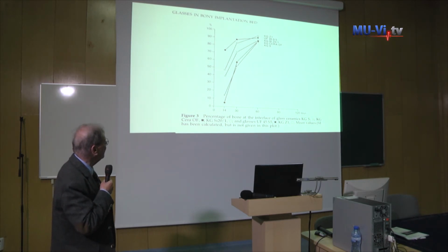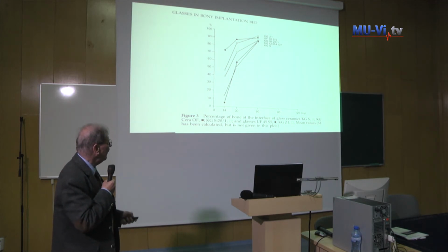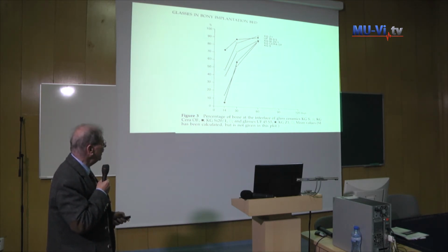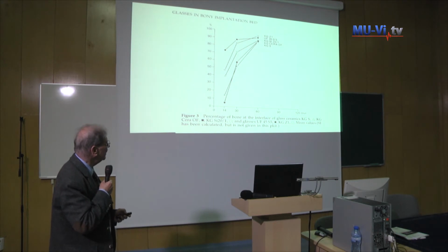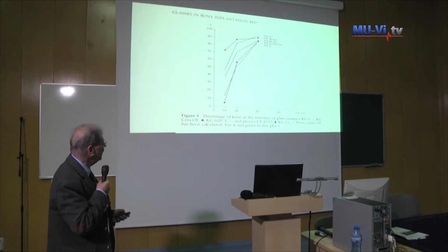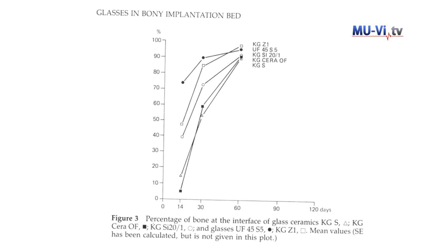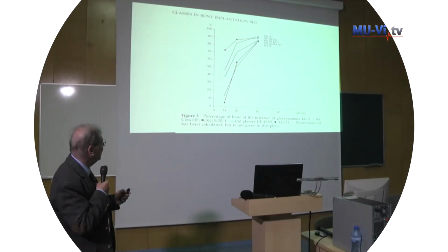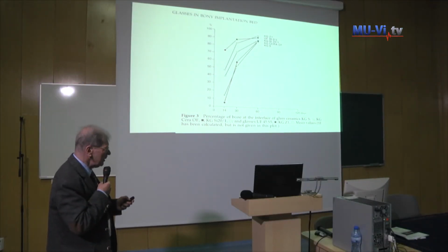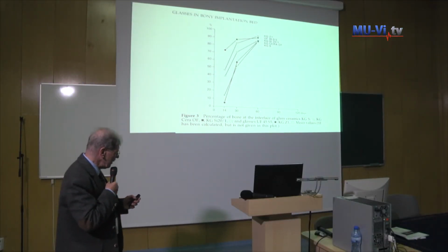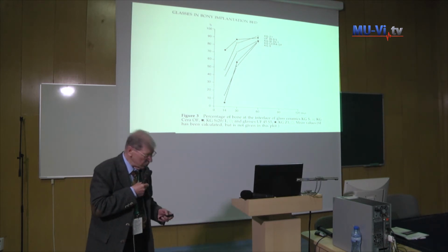These glasses of bioactive materials have the ability to cover the surface of implants very early, and after 60 days, for example, you see that up to 90%, 95% of the surface is mineralized bone.